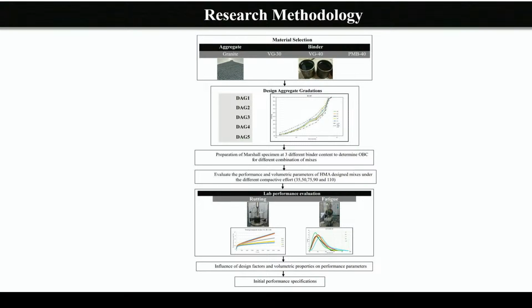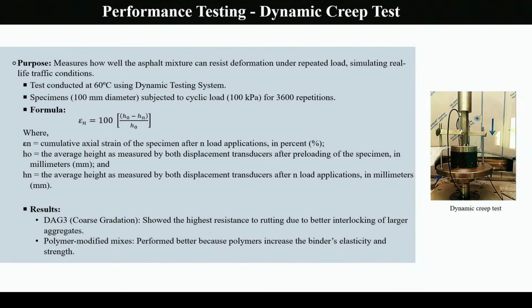So this was the research methodology we adopted for each type of mix. As sir mentioned, we need to have a simple, quick, reliable, and easy test to be performed. So, as we are using the Marshall design, we try to stick to the Marshall sample without the need of any further notching, cutting, or fabrication. So, the dynamic creep test is conducted in around 2 hours, and is used to calculate the rutting resistance of the mixture.